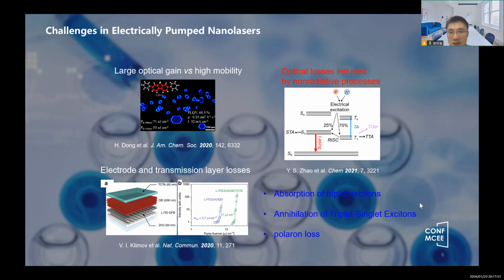In organic semiconductors, electrically injected carriers generate singlet and triplet excitons in a 1:3 ratio. In most cases, triplet excitons cannot produce stimulated emission and undergo absorption to high-energy triplet states, as well as annihilation processes with singlet excitons. These processes hinder the improvement of photonic performance and electrical pumping. In addition, the imbalance of electron and hole interaction in the material generates polarons, leading to additional optical loss processes.